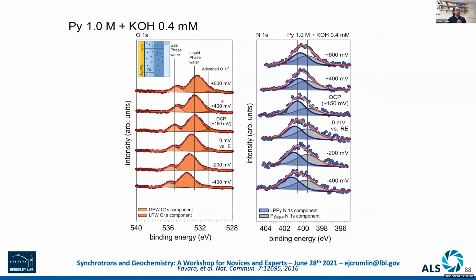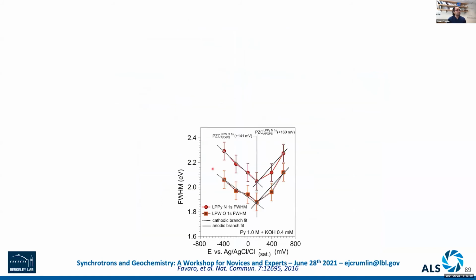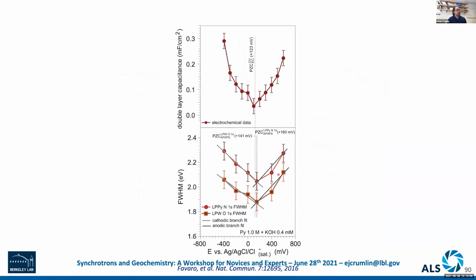So we're going to do this by looking at the oxygen XPS, and then we put in a probing molecule, pyrazine, and we'll look at the width change of the spectra. When we do this, we can see that there's a minimization at one potential, and then we get wider as we go away from it. The minimization is occurring at the potential of zero charge.